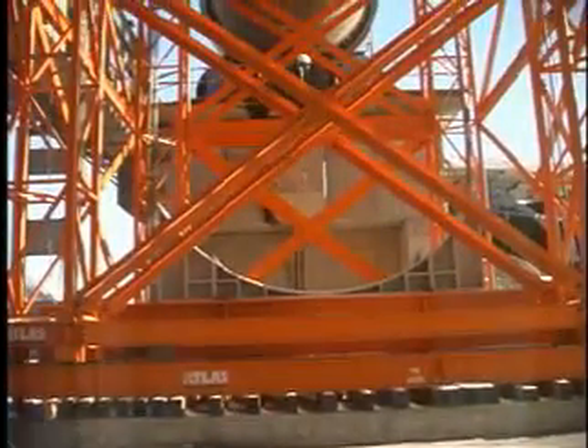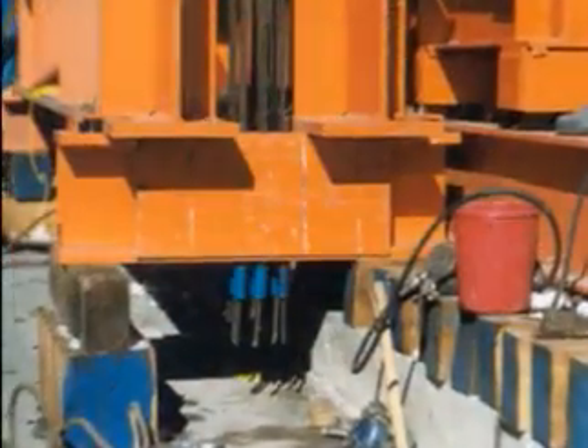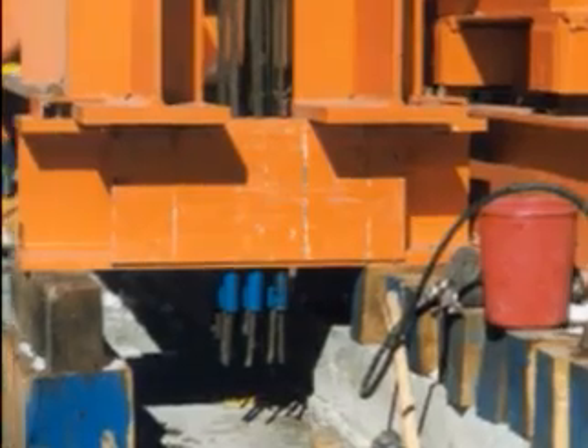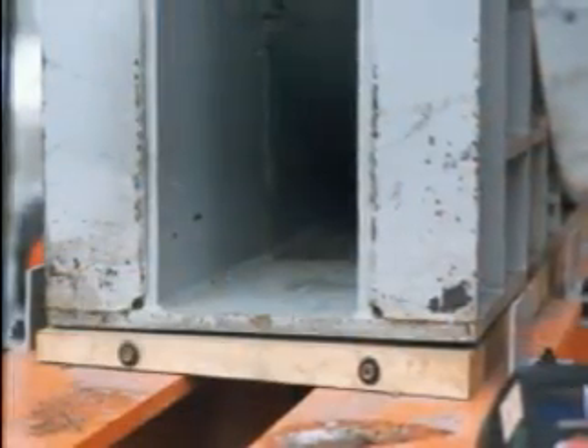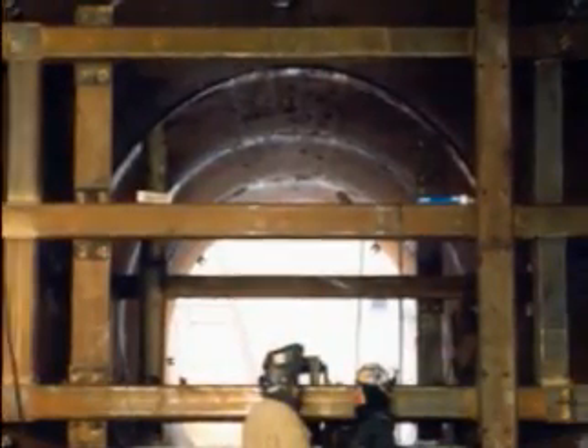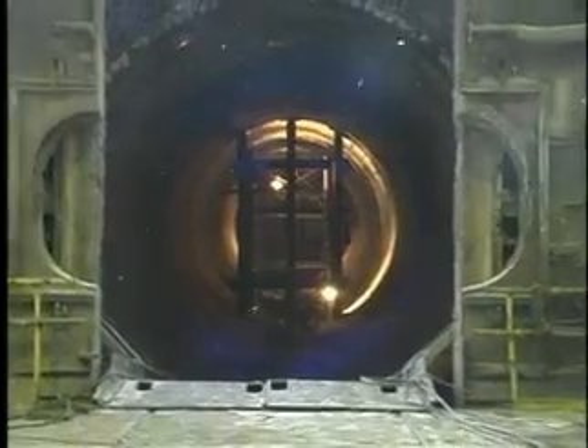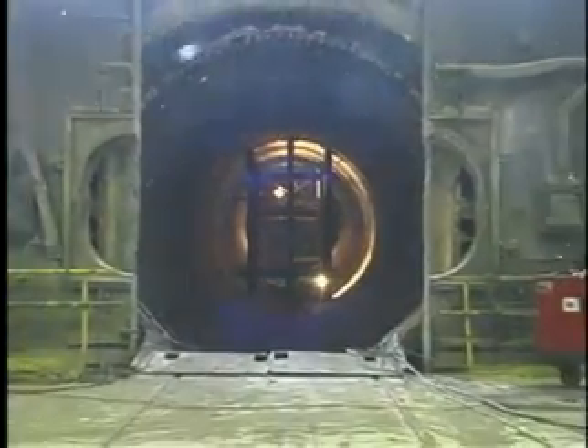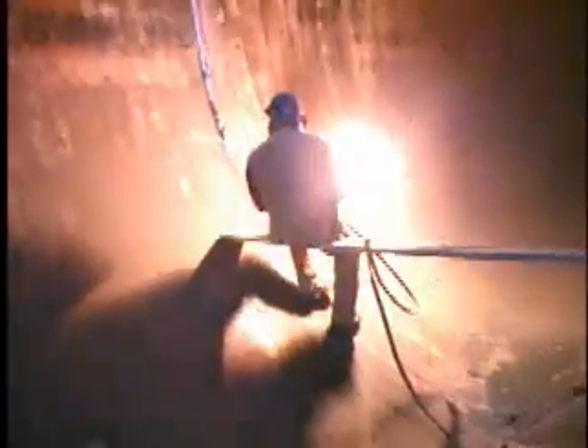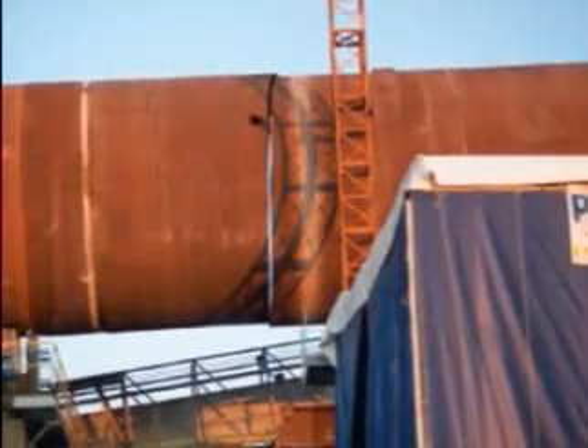These saddles were supported on twin sets of W36 lifting beams, where 4 sets of 12 3/4-inch strand cables were dead-ended. These saddles also required shimming to accommodate the 2.6-degree slope of the kiln. The kiln shell was fitted with inside spider bracing at saddle lift points, and the removal process started with the cutting of the kiln shell 1 foot outside the burner building wall and 30 feet upstream of pier number 2.